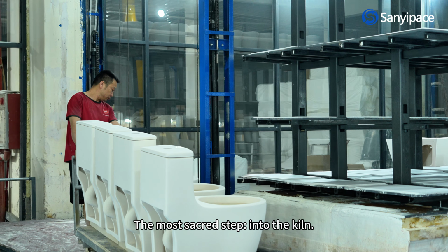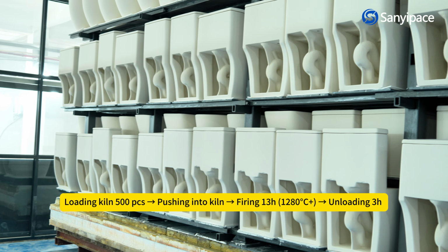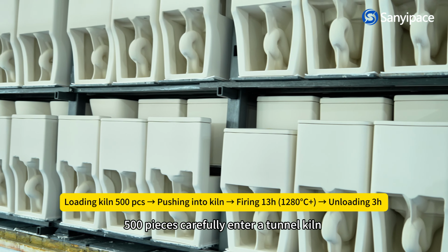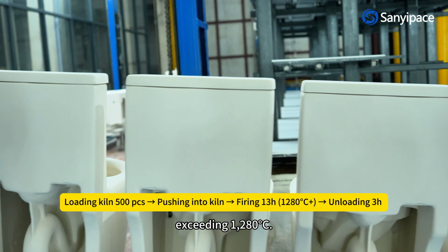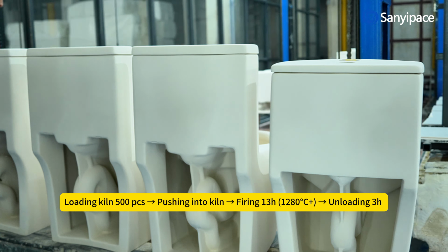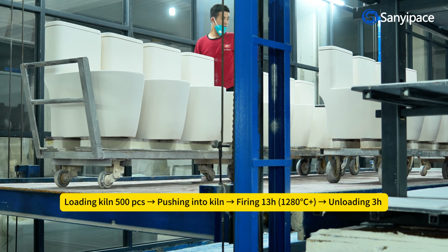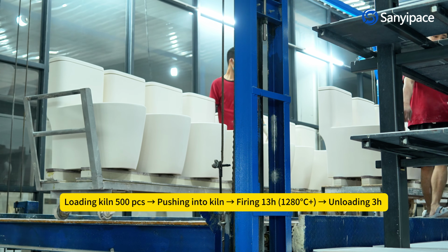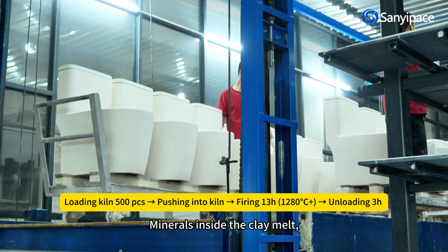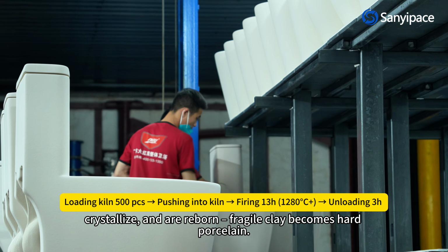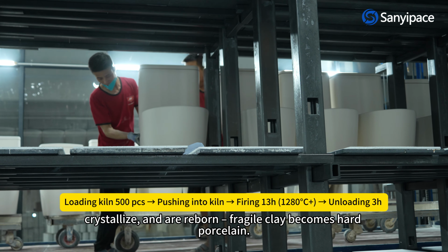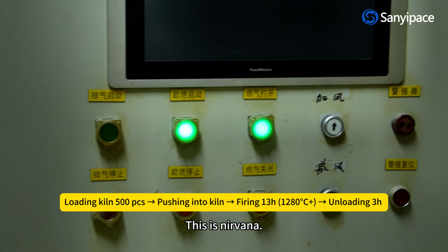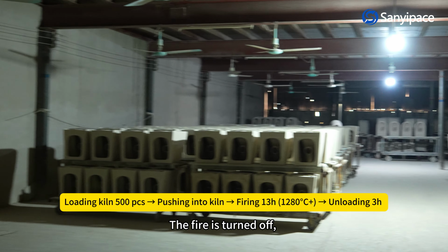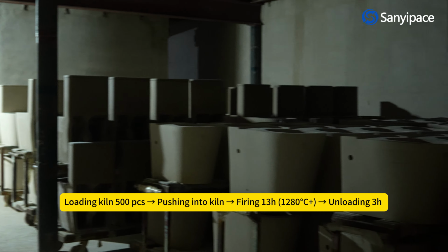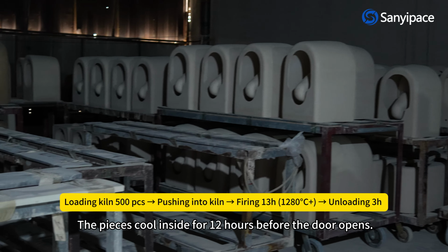The most sacred step: into the kiln. 500 pieces carefully enter a tunnel kiln exceeding 1,280 degrees Celsius. For 13 hours, fire engulfs them from all sides. Minerals inside the clay melt, crystallize, and our fragile clay is reborn as hard porcelain. This is nirvana. The fire is turned off, but the kiln stays closed. The pieces cool inside for 12 hours before the door opens.